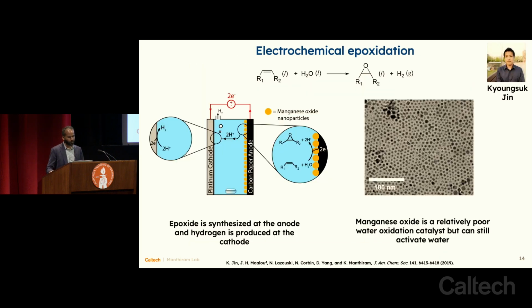So what we dreamed of in our group was that it would be really interesting if we could instead do epoxidation with water alone. If you could take an olefin, react with water, make an epoxide, and co-produce hydrogen. That really this is glorified water splitting. That instead of breaking apart water, making hydrogen, and struggling to recombine those oxygen atoms to make O2, and then just venting it to the universe, we could instead take those oxygen atoms and place them on an olefin to be able to make an epoxide.